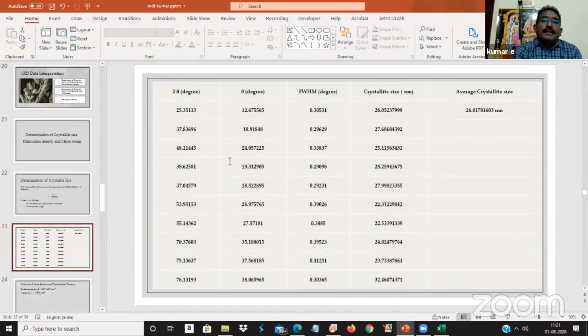The values are tabulated: the 2 theta value in terms of degrees, then it is converted into theta, then full width of maximum in terms of degree. Now we convert degree into radian. Now we substitute in the formula 0.9 lambda by beta cos theta. We get the crystallite size. The size of the particles is around 26 nanometers. The average crystallite size of the particle is 26.